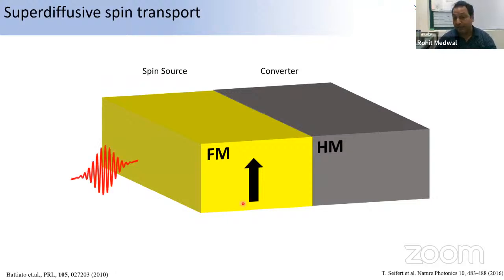When you shine a light on the ferromagnetic material, what happens? Basically, you excite the ferromagnetic material, and there are minority and majority spins in the system. As a result of this excitation, the minority spins are scattering, and the majority spins are also scattering. The minority spins scatter more because they are fewer in number and their lifetime is shorter. The scattering is high and the group velocity is quite low. So as a result, they never diffuse into the heavy metal adjacent to it. Whereas the majority spins are in the main number. They have fewer scattering events because they are in phase, and they go and get pumped into the adjacent heavy metal. And as a result of this, there's a quenching of the magnetization of the ferromagnet.